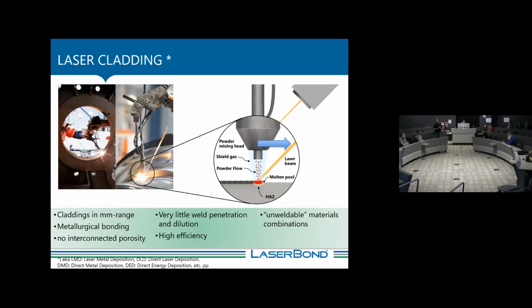The biggest advantage for me is to have a metallurgical bond between the cladding and the substrate. So no mechanical interlocking. We try to shield our part from the environment. No interconnected porosity, very little weld penetration, very high efficiency. That means that most of the powder actually stays on the part, whereas in, for example, the thermal spray process, sometimes only half of it stays.